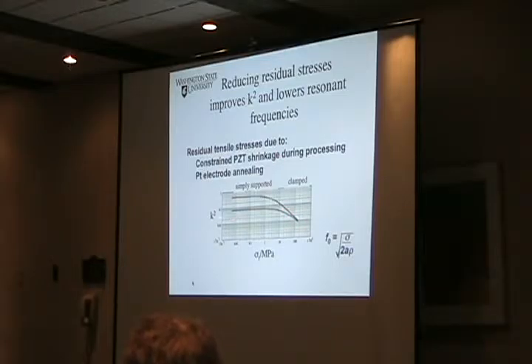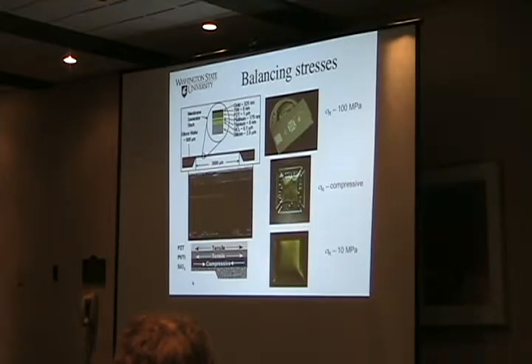Well, we worked out some modeling, and we should have our k-squared values increase as we decrease our residual stresses. So the residual stress in a piezoelectric membrane structure, kind of like we were making, is somewhere around 100 MPa, and the boundary conditions should make a difference once we're at low stresses, but at high stresses, they don't matter. So we thought, okay, if we just lower our residual stress, we will see an increase in our k-squared, and our devices will get better. That would be nice.